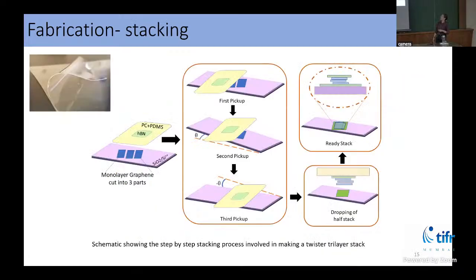Yeah, so once I have these 3 layers, I have the task at hand to actually make the stack. How I do it is with the help of this sticky polymer-like substance, a PDMS, as we call it, and it essentially acts like a stamp. Whenever I touch the graphene, it picks it up. So then I go in with this PDMS and pick up each layer successively on this stamp and make this stack. While I am doing that, since this is a twisted stack, I need to apply the relative angle between the layers. So in intermediate stages, I am rotating the graphene so that I get the twisted structure inside.